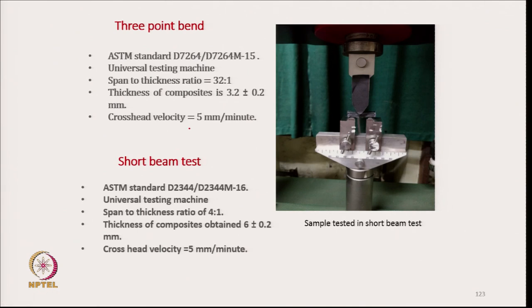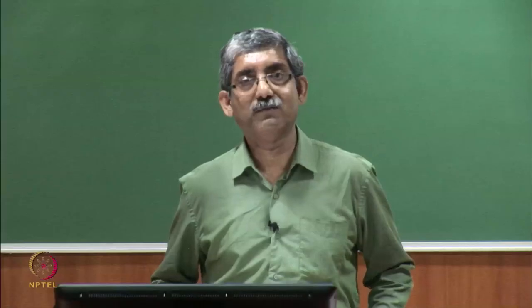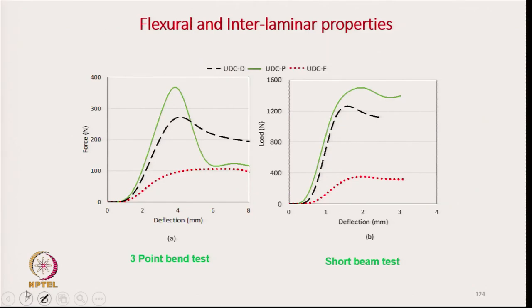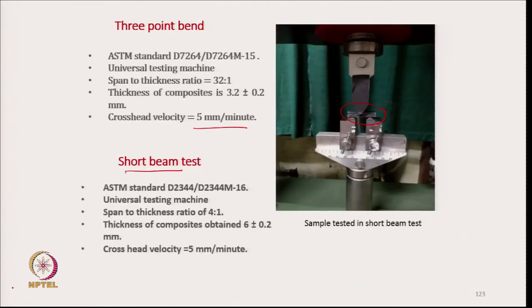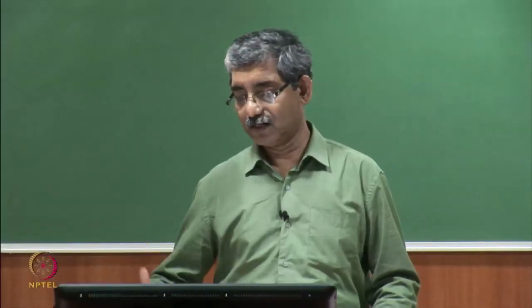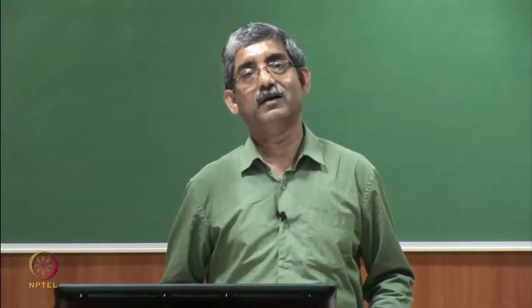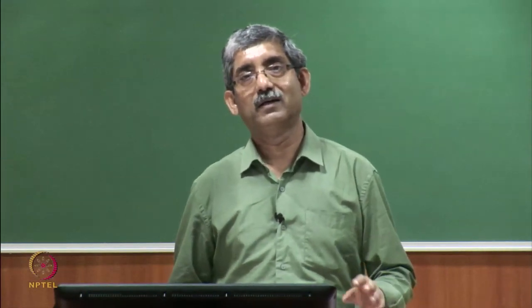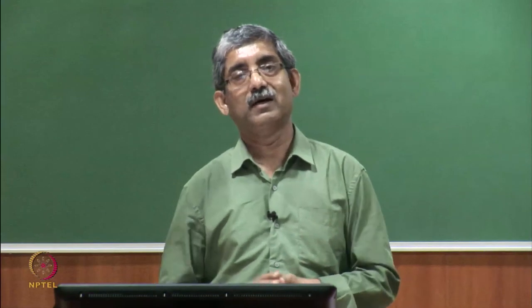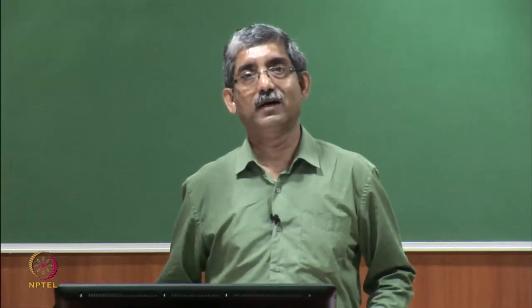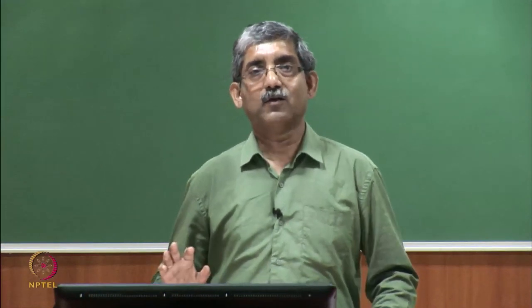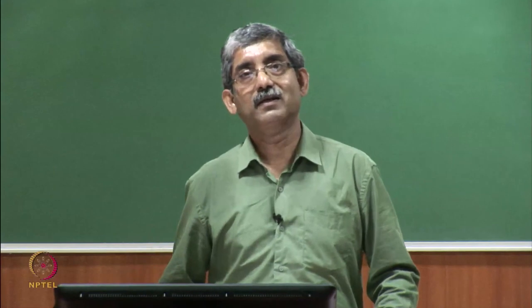For testing we have done the 3-point bending test with these parameters, where the crosshead speed is 5 mm per minute, and it is a short beam test, shown here, to get the flexural characteristics of the composites. We have done a detailed study for all these composites made from DREF spun hybrid yarn, film stacking and powder coating, and we have compared their results. All these results we will discuss in the next class. Till then, thank you.